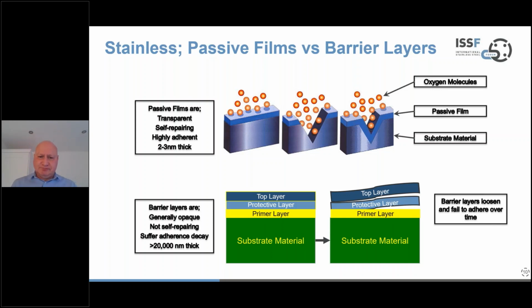Compare that to having to apply barrier layers, and typically 3 layers are applied. And when they're initially applied, all looks good. So you have the top layer, a protective layer, and a primer layer, which is the interface between the above layers and the substrate material. It's a much thicker barrier system, but over time, these layers loosen, and that includes galvanized coatings. We see all sorts of barrier layers ranging from paints to chemical coatings, but over time they do fail to adhere and they require ongoing maintenance. So a simple reflection of the 2 main options for protection against corrosion. One is driven by the chemical analysis and one is driven by man-made protection layers.